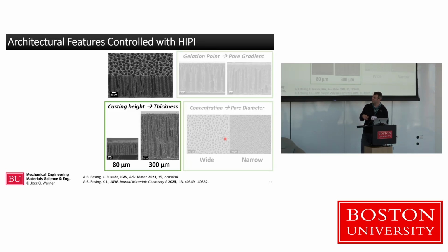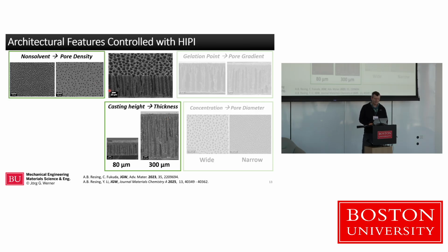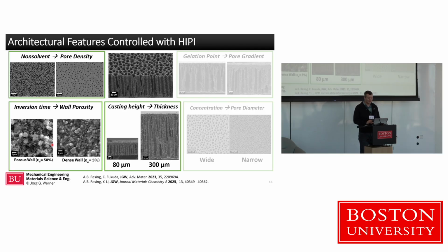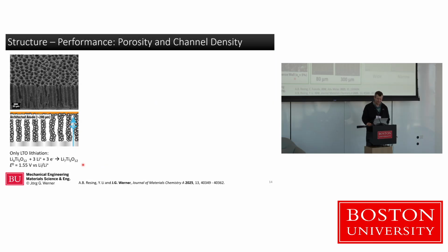I won't bore you with all of them because I want to show you some battery data, but really the most important ones are, of course, that we can make them thicker or thinner, so we can change the electrode thickness or height. We found that the non-solvent, that immersion bath, has a very strong impact on how many of these channels we have, so we can go from hundreds and hundreds of these channels per square millimeter down to a few tenths. So a couple orders of magnitude we typically can tune, and of course we can get 0 if we want to. And we found something that wasn't really established: how can you tune the porosity within these walls? We found that how long you leave it in the bath really impacts that, where we can go from essentially no porosity within these walls to very porous walls fairly seamlessly.